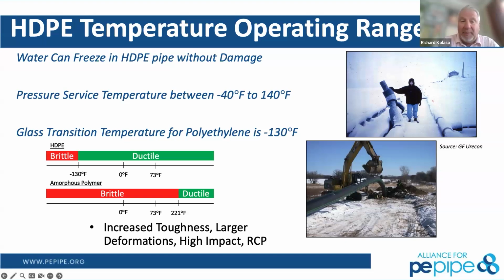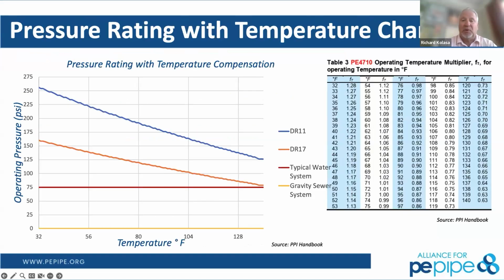But if you're trying to bend pipe around corners without fittings or transitions, and you're in that allowable zone of the allowable bend radius, you have that ability. But the forces required might be a little bit greater because it is a little bit more dense. Whereas amorphous materials, such as PVC, they're brittle right at 221 degrees. So they're a brittle product. So having any bending or movements or moments on those pipes can add really intensified stresses on those products. So you do have that luxury, but know that it does change as your temperatures go down and up. So it becomes more flexible when you go higher and less flexible when you come down.